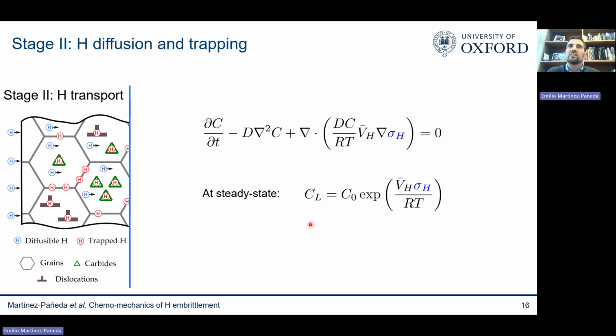You can see here, this is the steady state solution for this equation. You can see that the hydrogen concentration has this exponential term where again, the hydrostatic stress is inside of that exponential term. So the hydrogen content ahead of a crack is going to be much, much higher than elsewhere.